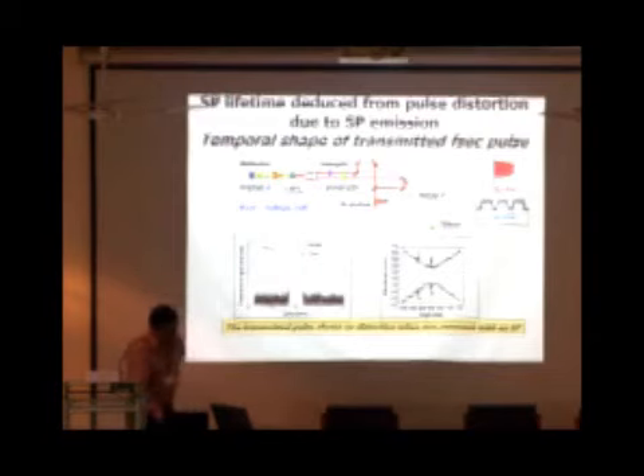But what's interesting is when you choose a resonant wavelength. For example, we choose 750 nanometers, which is at the long wavelength band edge of the plasmon, you see there is a slight change in the shape.